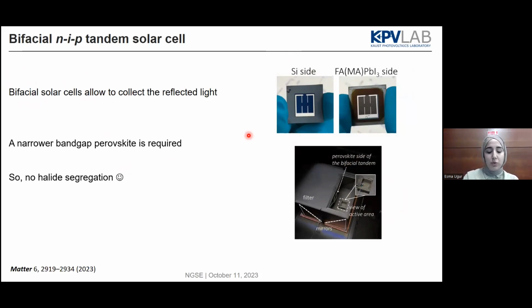So for this one, now we don't need to have the current matching condition, so we can go to the narrower bandgap because we will have more light from the silicon side. So we can have the narrow bandgap. Here, what I use is 1.55 eV. And it's the pure iodide system, so we don't need to think about the halide segregation. So how we are measuring these devices, basically, you have the full one sun condition from the top of the device, and we use different filters to mimic the reflected light from the back.